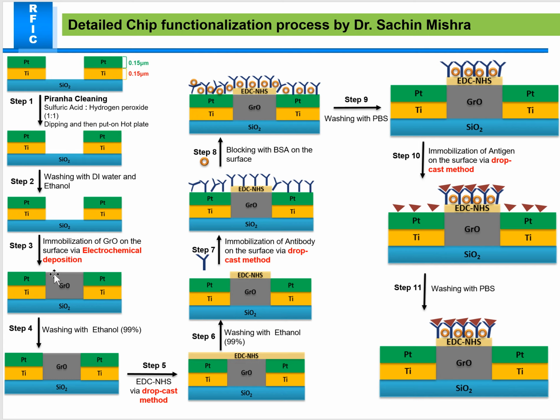So here I have made a clear visualization: after electrochemical deposition the graphene sticks onto the SiO2 surface, which is an open surface in between the fingers. After washing with ethanol, the graphene is totally deposited in between them, and since it's electrochemical deposition, there is no chance that after washing the graphene oxide is removed or peeled out from the surface.